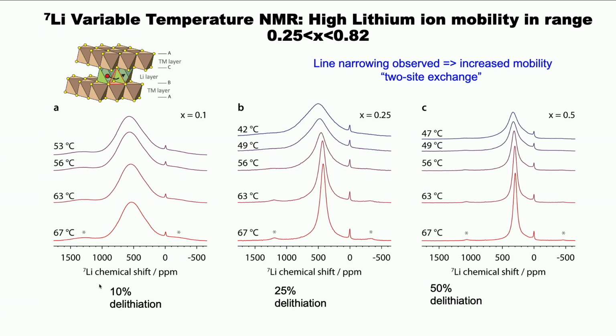But if I pull out 25% of the lithiums, I now have vacancies in the lithium layers, and the ions can start to move. And the signature of motion is quite clear from when you heat this material up. Because the ions are moving, they're changing their local environment, and so you get what's known as motional averaging. So the NMR only sees the average environment of the ions moving in these layers. And you can see by the time you got rid of 50%, you've got very high lithium mobility.